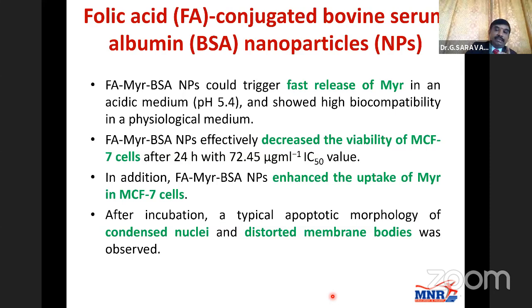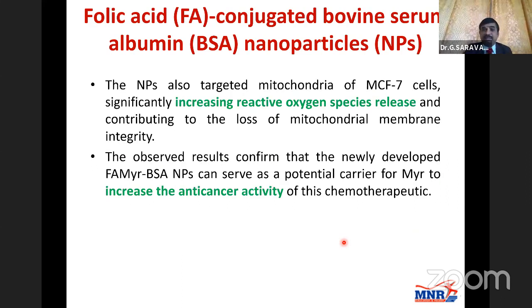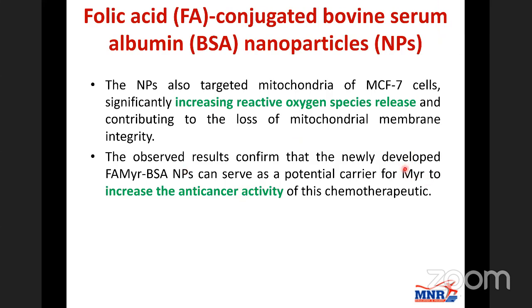From the study, we found that these nanoparticles rapidly released myricetin in an acid medium. In the physiological medium also, it released myricetin in a faster manner, and it decreased the viability of the MCF cells after 24 hours and increased the uptake of myricetin molecules. After the incubation period, we also observed apoptotic morphology, with condensed nuclei and distorted membrane bodies. In addition, it increased the release of reactive oxygen species, which contributes to the loss of mitochondrial membrane integrity. So finally, we concluded that myricetin's anti-cancer activity is increased. The drug molecule we took is myricetin.